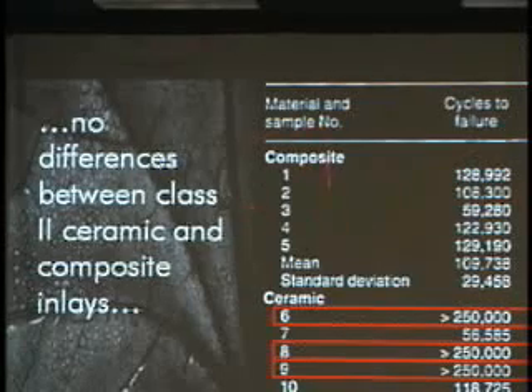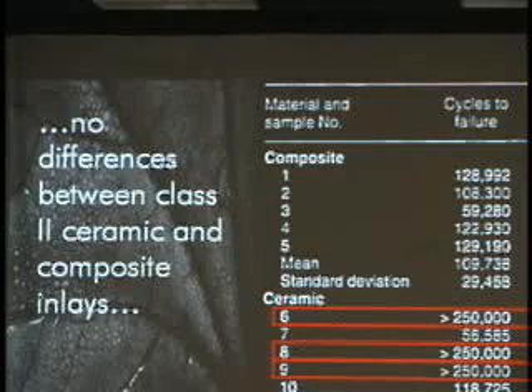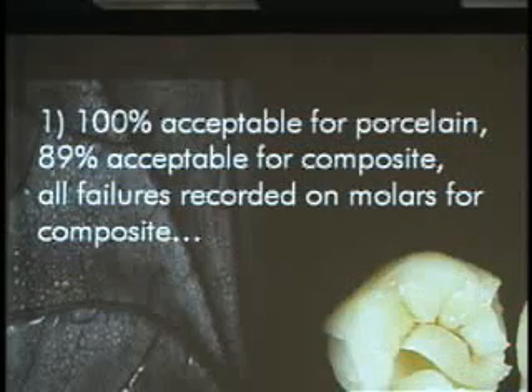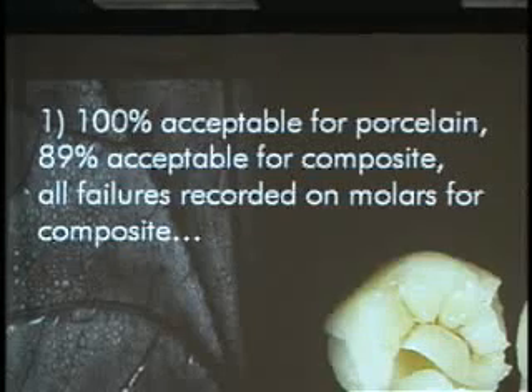The interesting thing is that of the 5 ceramic restorations, 3 of them did not fail after the test, while on the composite restorations, as you can see, all of them failed after the test. There was failure obvious for all of them, but statistically not significant. But still interesting. There is a trend that ceramic is more able to stabilize the cusp and more able to maintain the biomechanical integrity.